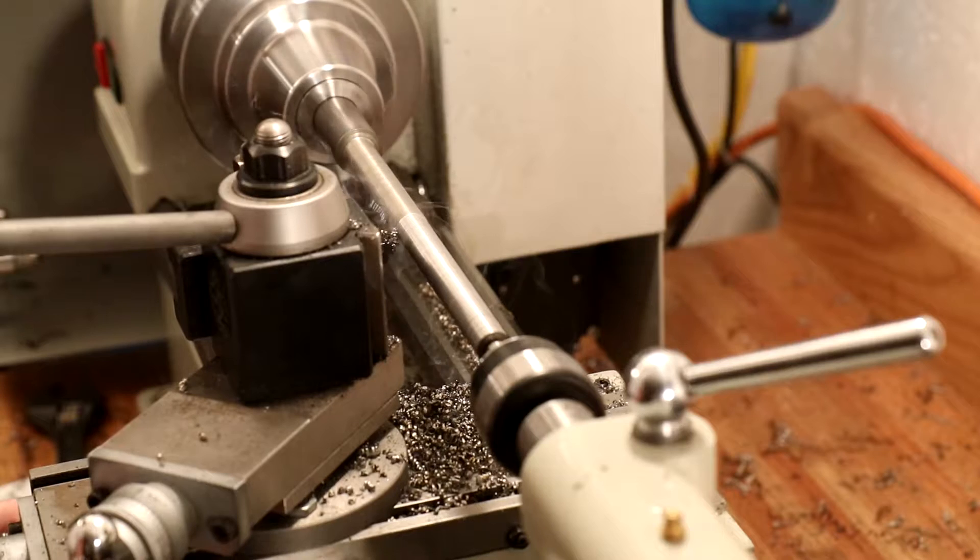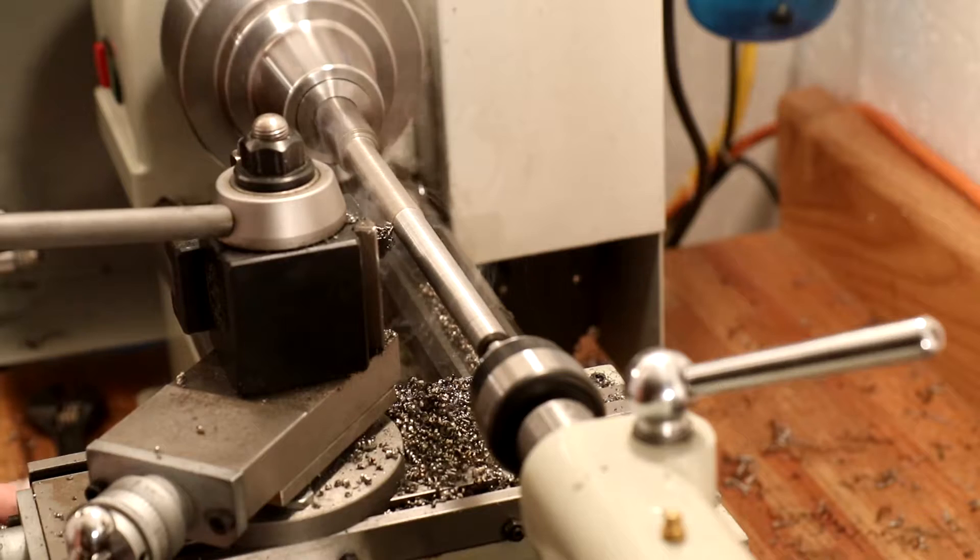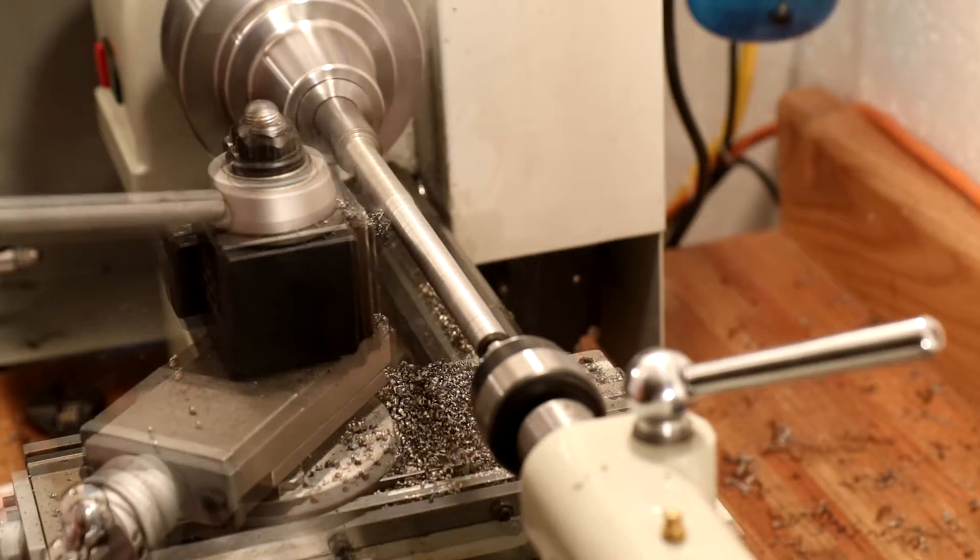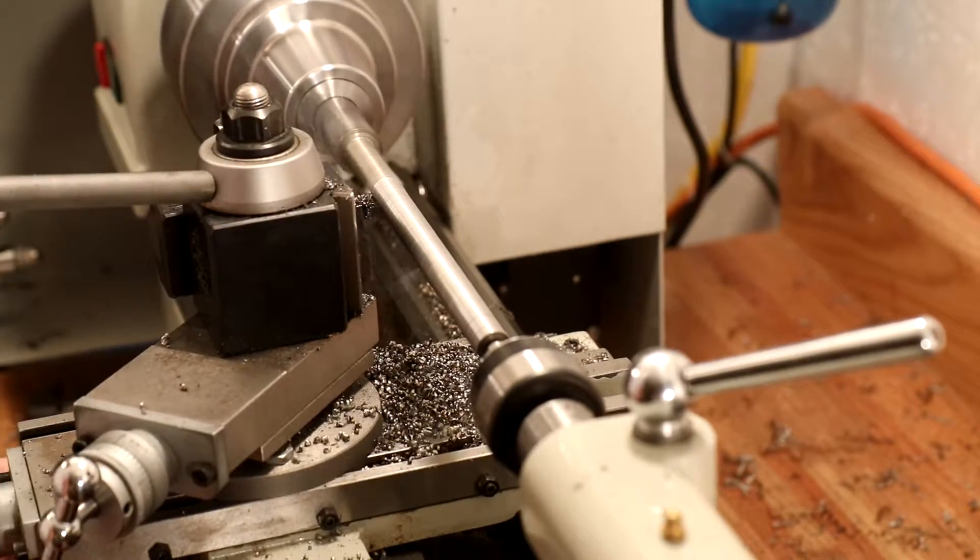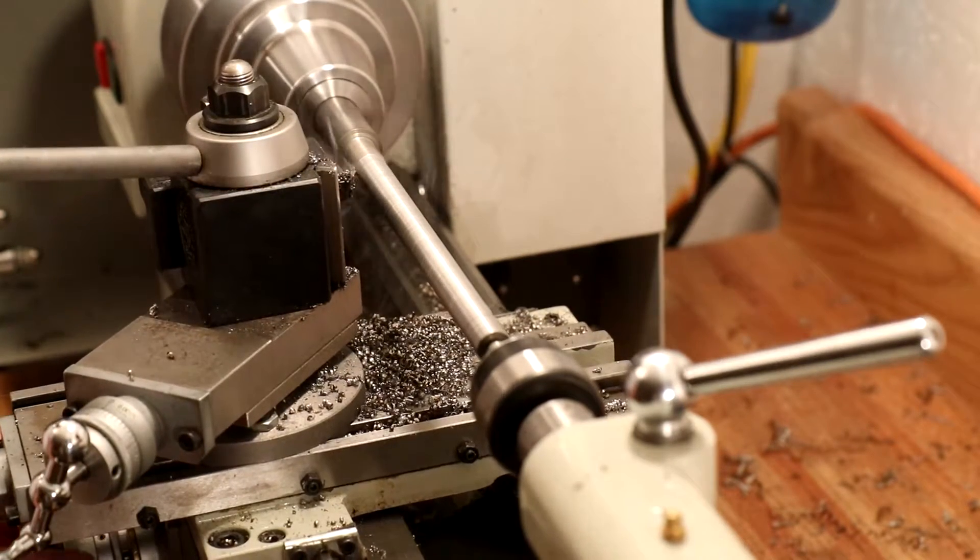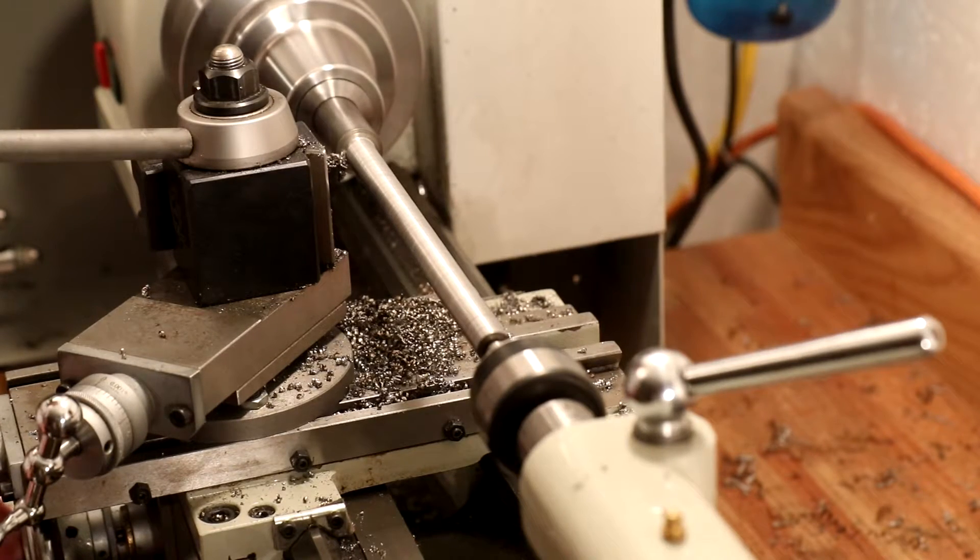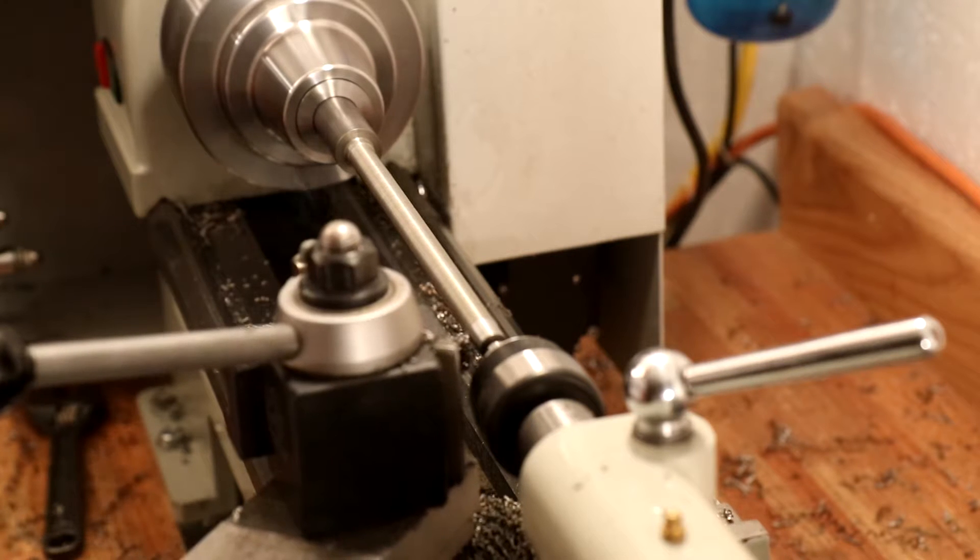A high-speed steel insert tool seemed to cut better than the carbide tool did. I think the part was work hardening while turning, and the coolant and the cutting oil helped, but it just wasn't enough. It was possible to actually see this happening as I was cutting with the carbide tool. The material would become shiny and resistant to cutting, and the best I could come up with is just to push the tool harder and get underneath that hardened surface and continue cutting.